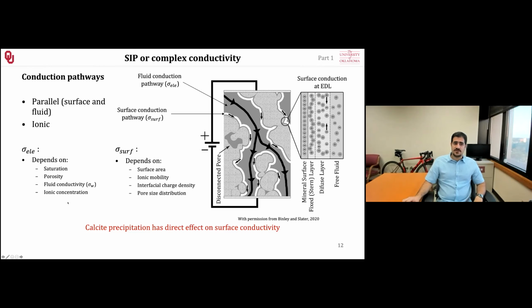Now, the surface conductivity, basically the polarization that was happening in here, the redistribution of ions in the double layer, depends on the surface area and not only saturation. Basically, the more grains you have and the finer they are, you have more polarization. You have more surface area to get polarized, more surface ions. And then in that surface area, if the ions are bound as they are and they're not mobile that much, you can actually measure that as well. So the ionic mobility also affects the surface conduction and the polarization as well.